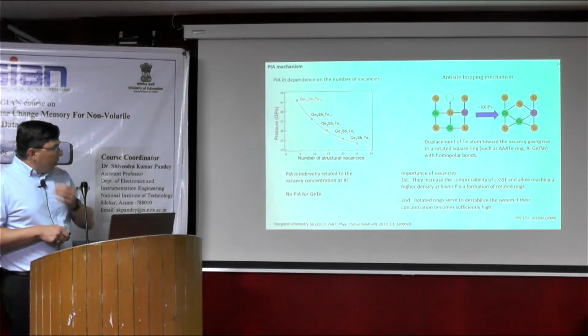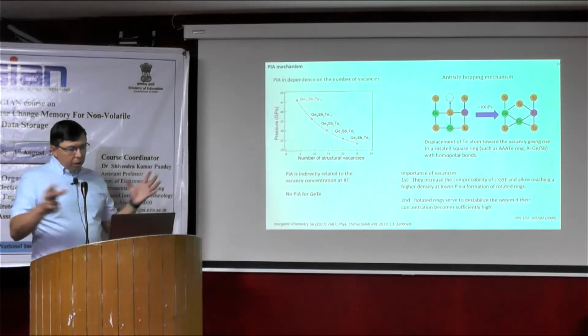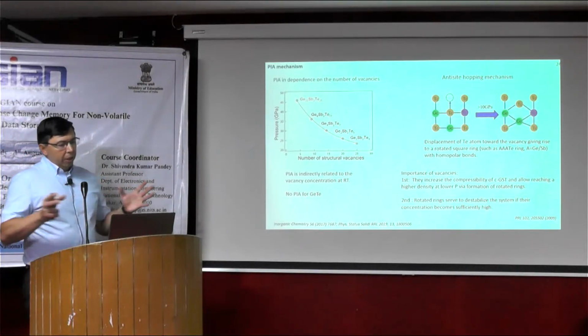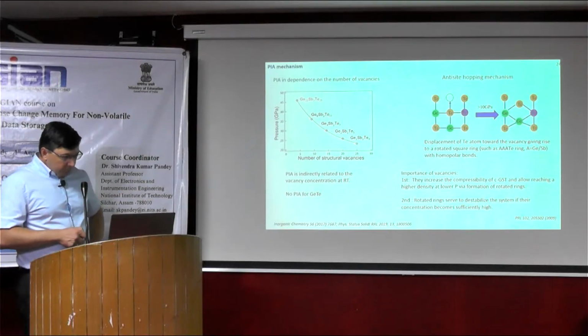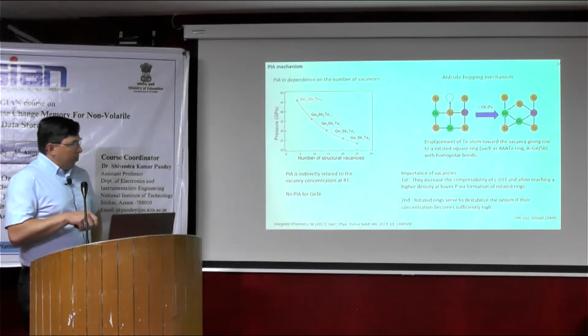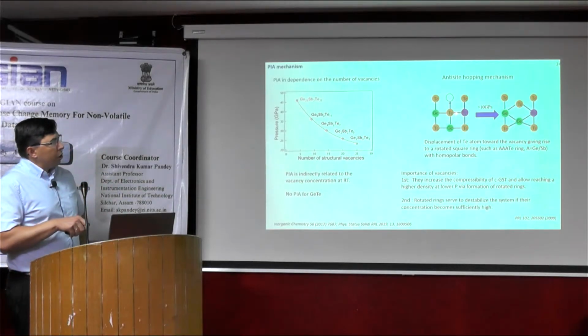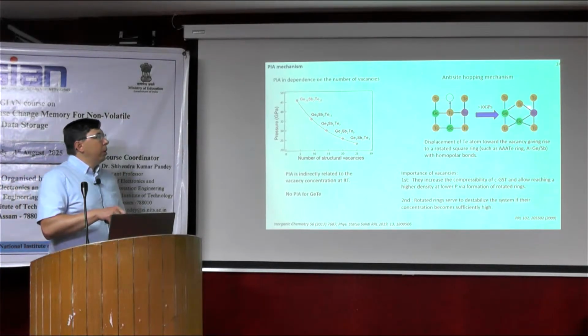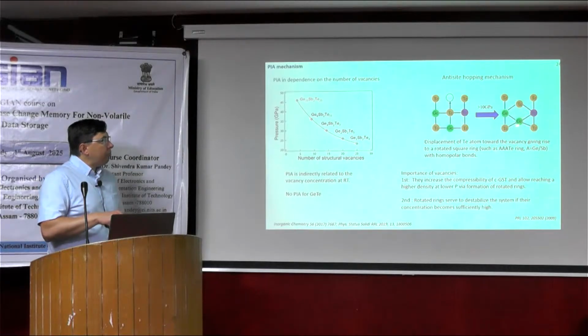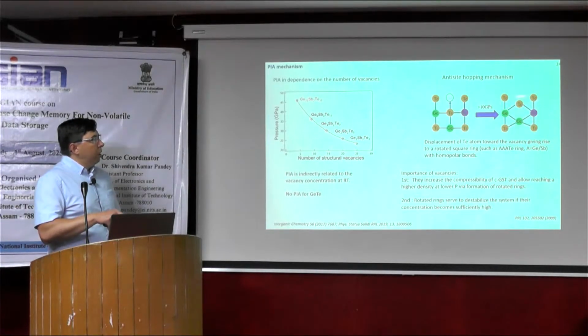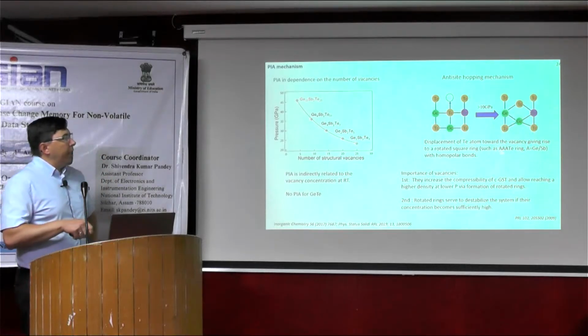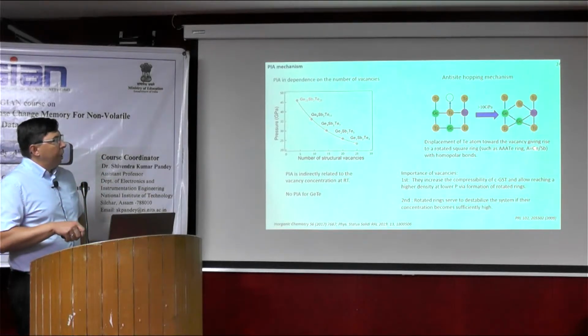What happened here during the compression? We know already that the system can get a little bit denser. And here, what happens is that tellurium shifts to the vacancy, like here. Then we have a new structure having tellurium, germanium, germanium, tellurium. So it forms an A-A-A tellurium ring. The A, this is germanium and antimony.